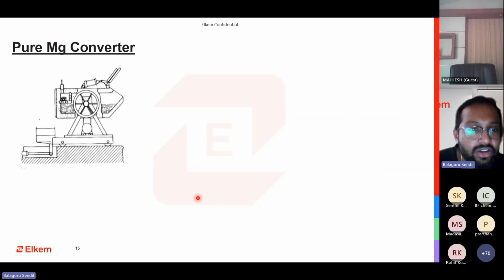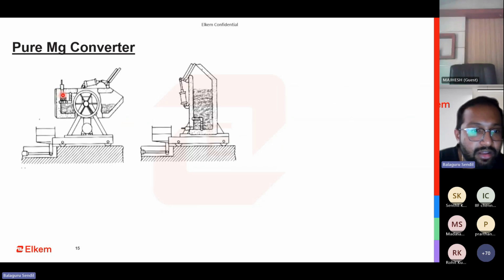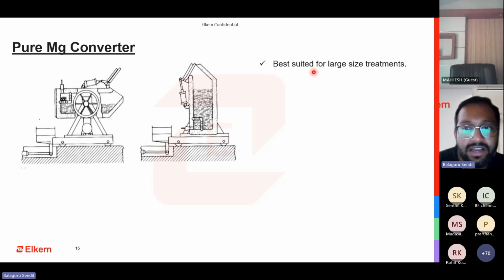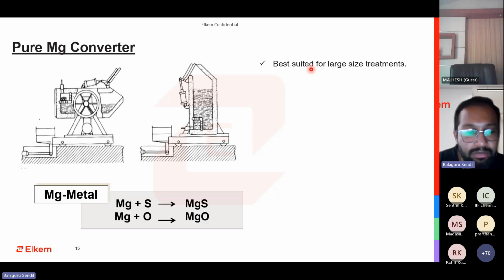If you go for the pure magnesium converter, as I told you, you have the option of putting the pure magnesium ingot alloy here. People have modified this and also started putting ferrosilicon magnesium here and tilting it. It has its own advantages and disadvantages. It is best suited for large size treatments. When you are using pure magnesium, the magnesium can only form MgS and MgO. These are the two compounds that can form, because we don't have any other. The magnesium is 99% or nearly 100% pure metal. There is no other element present here which is going to help the case of nodularizing. But unfortunately, magnesium starts melting at 650 degrees Celsius.